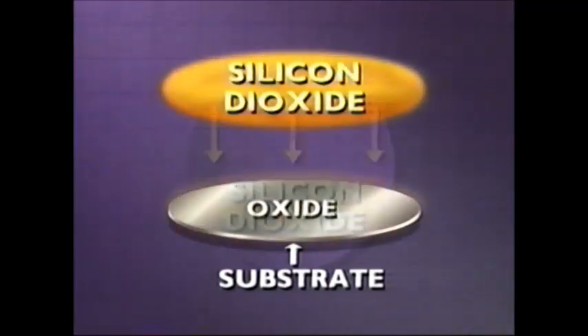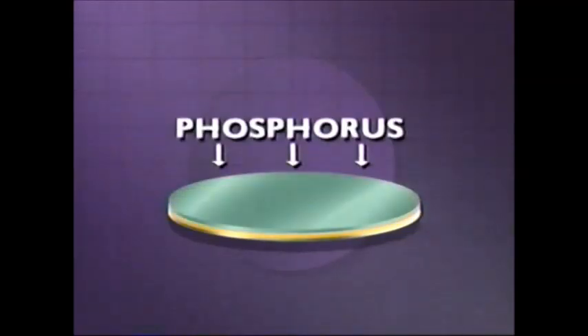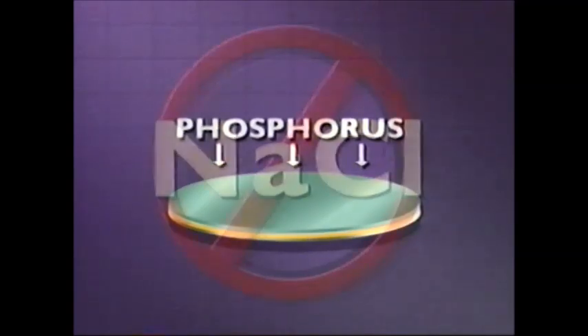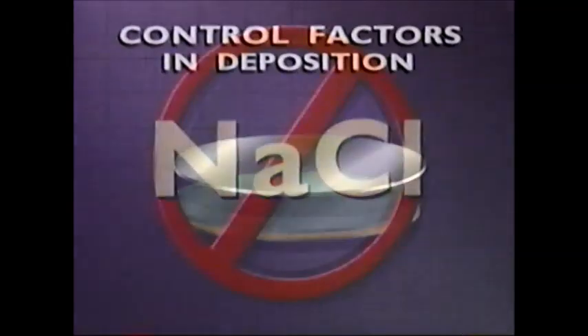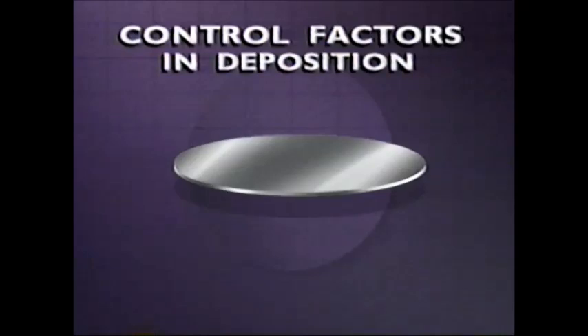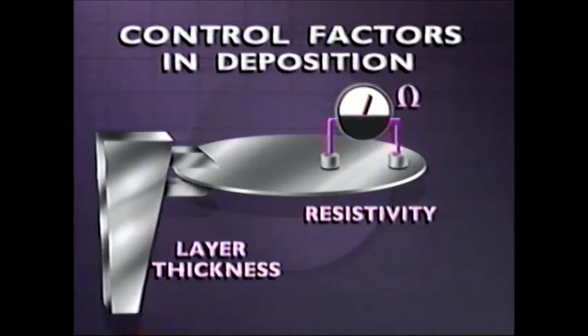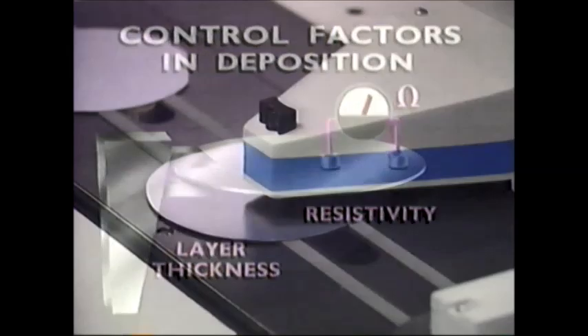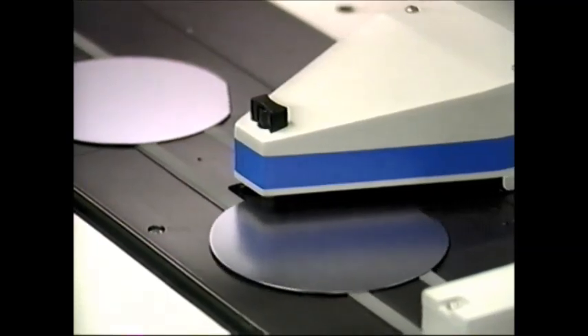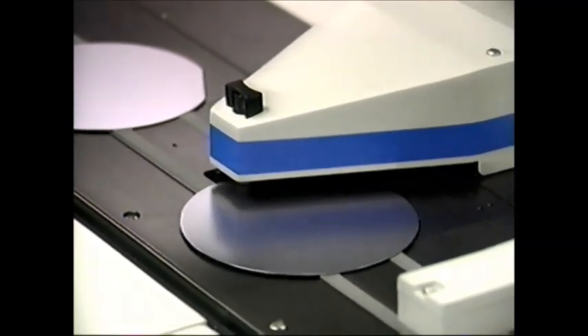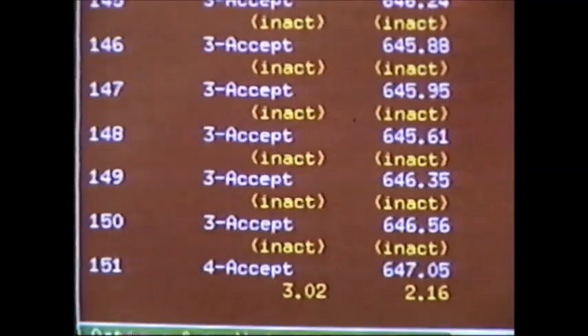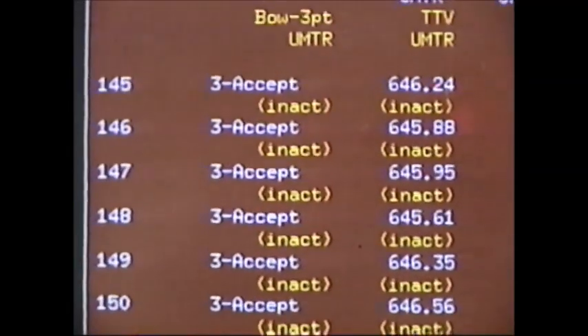Silicon dioxide layers are deposited on the wafers as a protective coating during fabrication or as a mask for high-temperature deposition or implantation. By adding phosphorus to the silicon dioxide, the deposited layer also acts as a sodium barrier. The 2 most important control factors in deposition and growing are layered thickness and resistivity. These and many other wafer parameters are constantly checked throughout the wafer fabrication process to guarantee high-quality, high-yield processing.